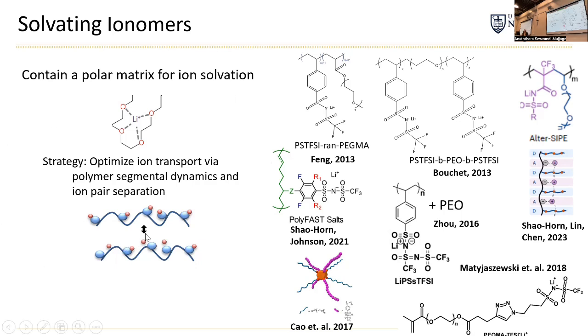And so we know kind of how to optimize these systems. And in the past couple of years, there have been some advances. I'll just point out a couple of preeminent works in the literature right now. Shao-Horn and Jeremiah Johnson's group published on this polymer in 2021, where they created a tunable anion that's tethered to the polymer backbone. They mixed this with polyethylene oxide. But here, these R groups, they were able to swap them out for different chemical functionalities, which made the anion better able to interact with the polyethylene oxide.